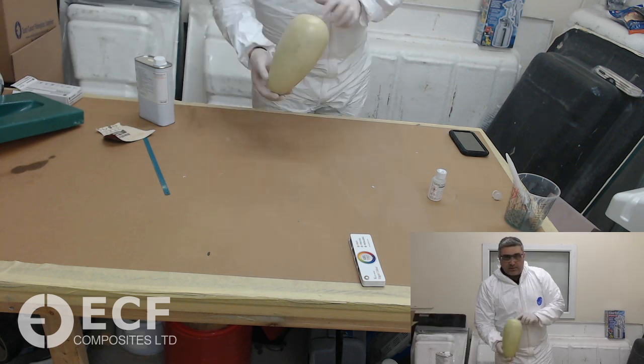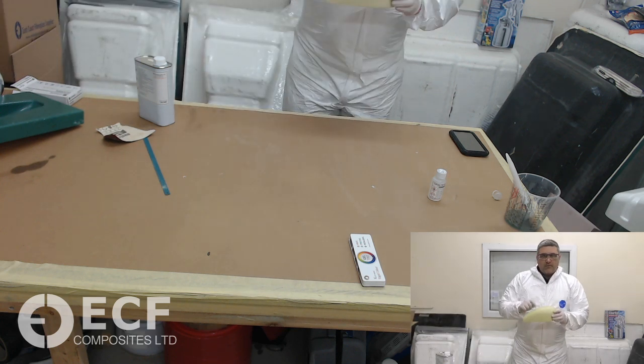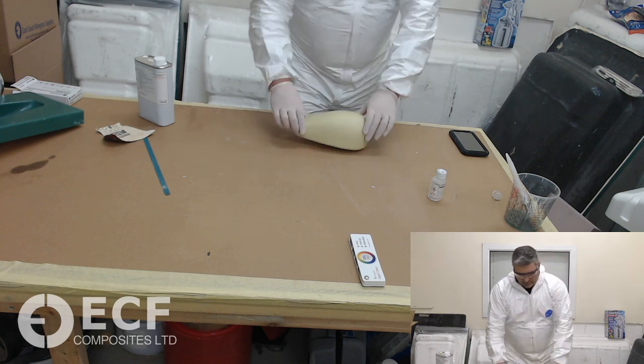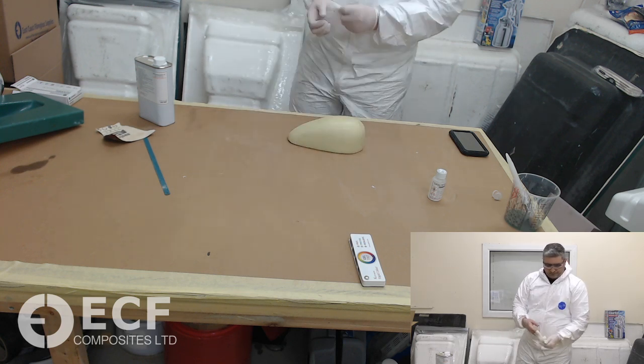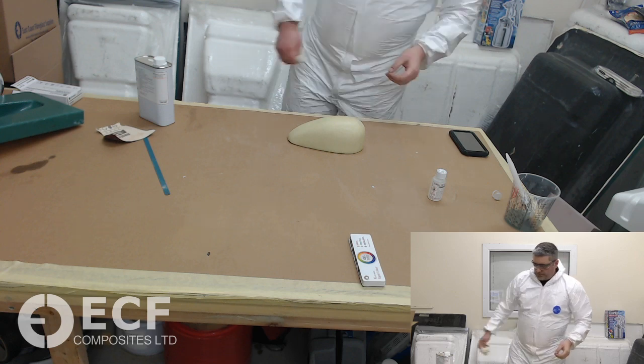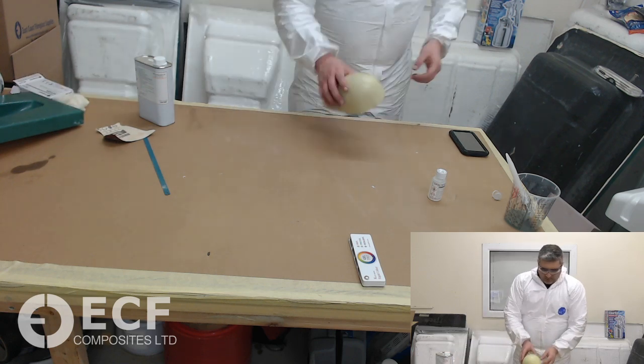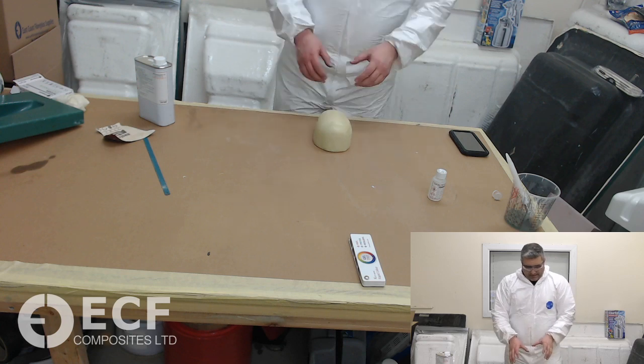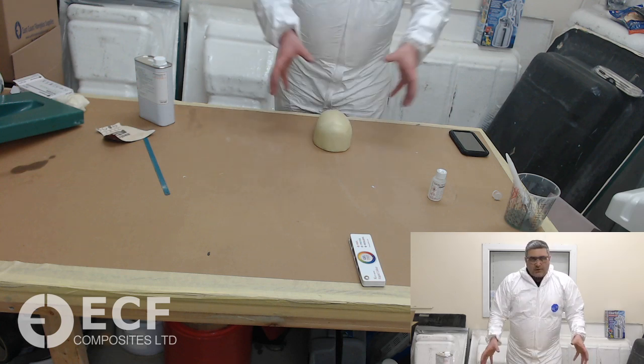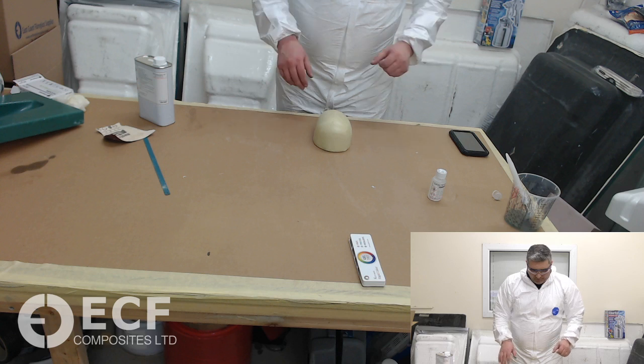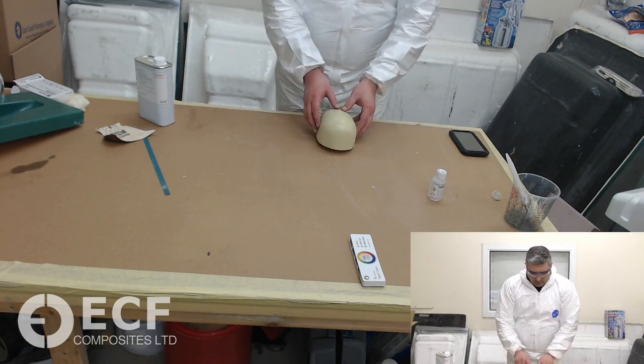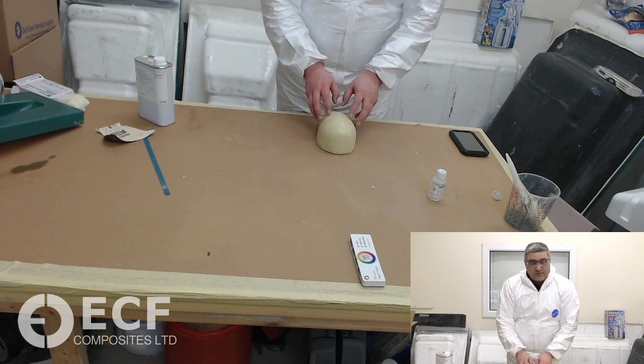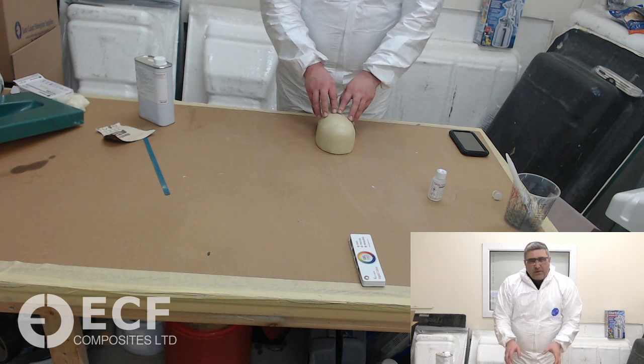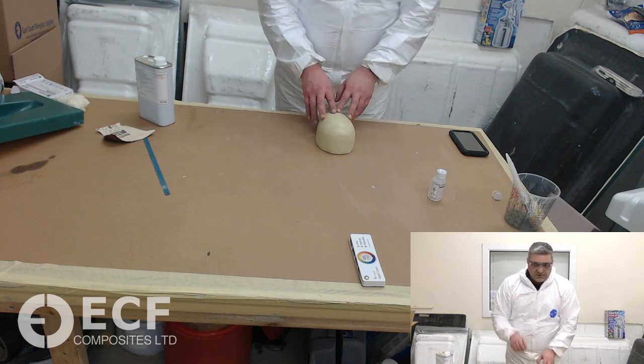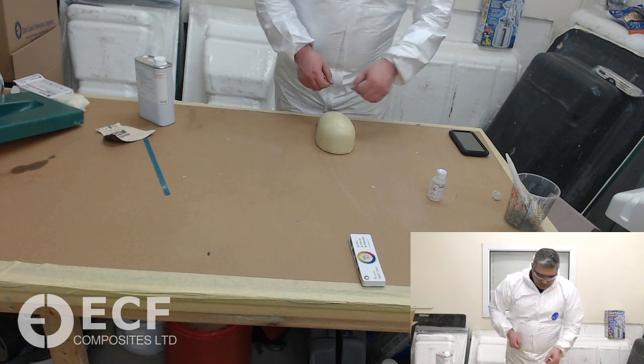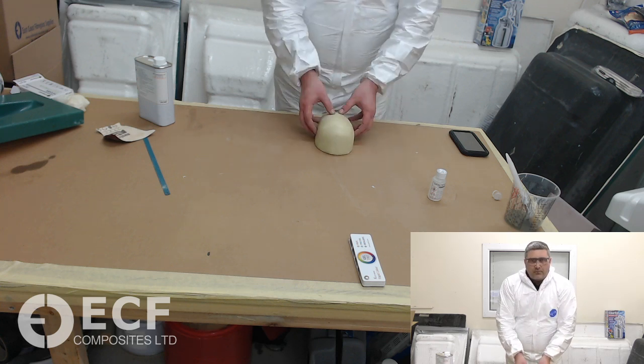And here's one that's been done earlier. It's done nice and hard. It's no longer dusty. But the problem with this material is, if this was a slightly larger part that we were doing, especially with a flat surface, although the surface is now sealed, it wouldn't be quite hard enough to mould from. Once you start working with resins on top and start paddle rolling it, you'd probably crack that outer shell.